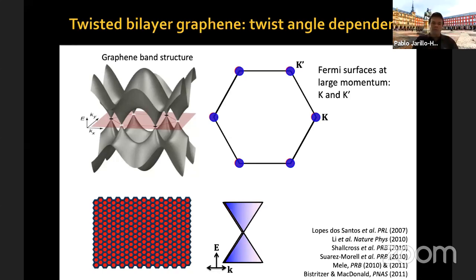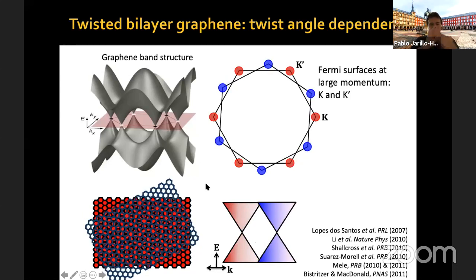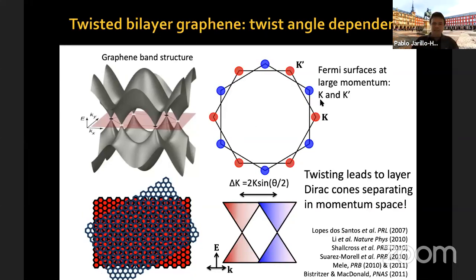to create a moiré pattern. So now, what happens to the electronic structures when you create this moiré pattern? If you rotate these two lattices by an angle in real space, it turns out that the reciprocal spaces also rotate by the same angle.